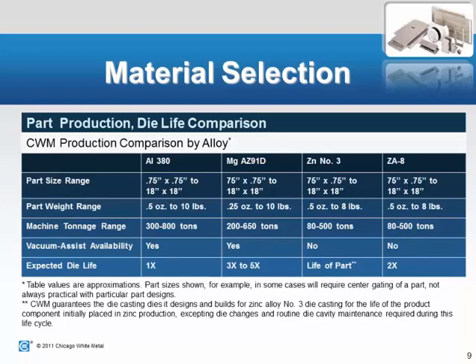The expected die life is an interesting thing to talk about. People always ask, how many shots can I get out of my tool? And it varies by the alloy that's going to be run. We use aluminum as kind of a baseline, which is why we have the 1X shown there. So if, let's just use a number, 100,000 shots that aluminum tool can shoot before seeing some things on the parts that are going to require some tool modifications or refurbishment. That number may be higher or lower based on the application and cosmetics required, but if you just use 100,000 as an example, magnesium, you should be able to get about 3 to 5 times that than aluminum with the